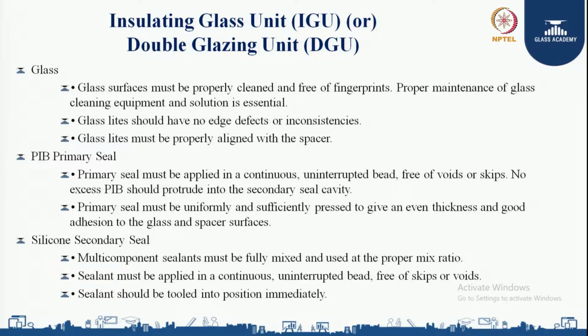Silicone secondary seal: multi-component sealants must be fully mixed and used at the proper mixing ratio. The sealant must be applied in a continuous, uninterrupted bead, free of skips or voids, and must be tooled into position immediately.